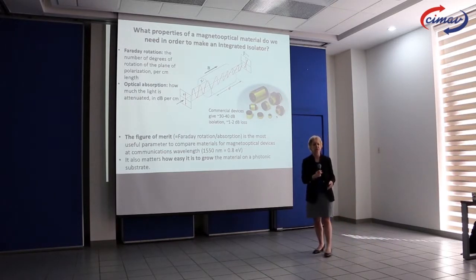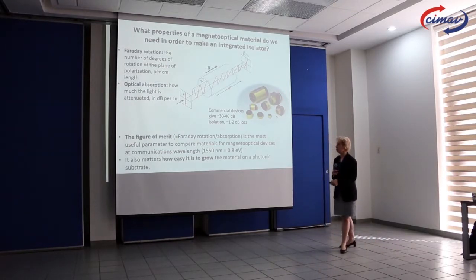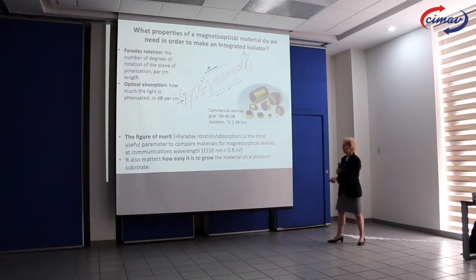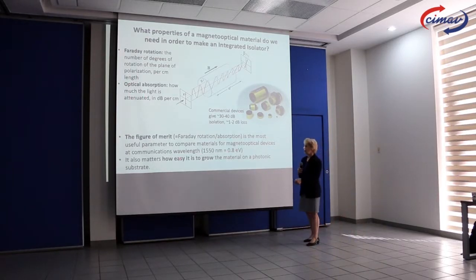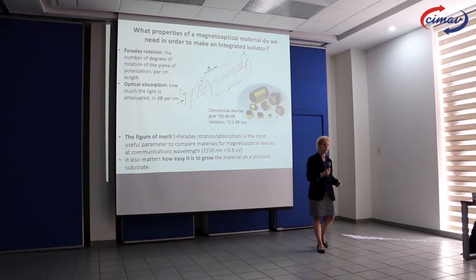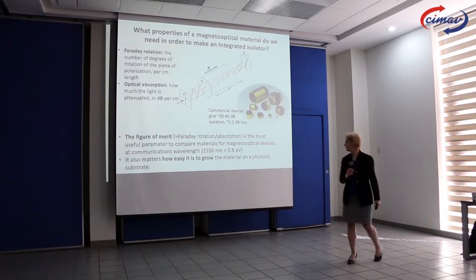So we want to be able to make materials to do this on chip. We need the material to have a good figure of merit, so a high Faraday rotation, a low optical absorption at the relevant wavelength, and we need to be able to grow it on a silicon platform.